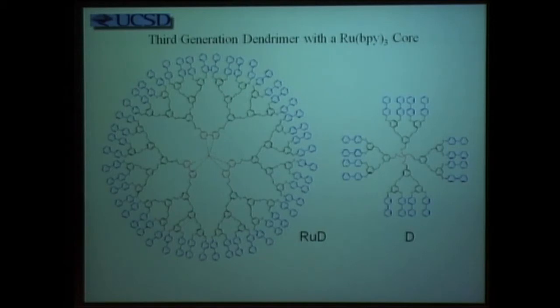If we go further, you can see that even trying to draw this molecule creates vacancies near the Ru(bpy)3 core. And we found that the vacancies are an additional way of controlling chemistry, because only those molecules that are of the correct size to migrate in toward the center of the oxidation reduction catalyst will be activated. Those that are too large will be excluded. So you can selectively oxidize or reduce a chemical according to its size and access onto the central core.